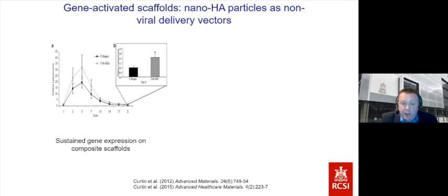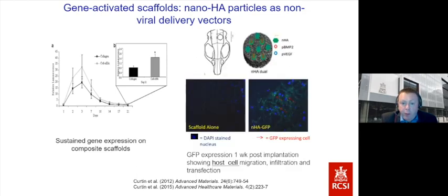And the idea is, next slide please, that if you put that gene-loaded scaffold into a defect, and in this particular example, I'm showing you a rat calvarial defect, so a hole in the rat skull. The scaffold, in this case, loaded with nanoparticles containing green fluorescent protein. It goes into that defect, and at 1 week post-implantation, what we can see, because the cells are now fluorescing green, it shows that we're getting host cell migration, infiltration, and transfection. So that shows proof of concept.